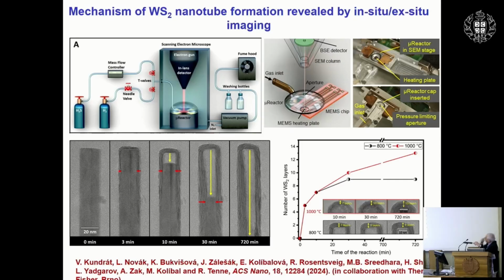So imagine for yourself a microreactor that is placed in the SEM, and then the microreactor works at a few millibars of hydrogen sulfide pressure flow and hydrogen and a temperature of close to 1,000 degrees, actually 1,000 degrees. So if you think of that, if this hydrogen sulfide will evaporate from the microreactor and leak out from the microreactor, in about 5 minutes you will have no microscope.